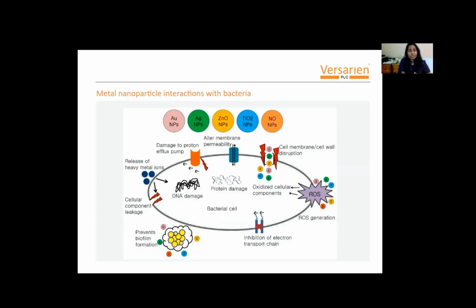Then to talk about the metal nanoparticles, for example in graphene-metal nanoparticle hybrids, the most active ingredient here is the metal species. Release of heavy metal ions can happen into the cell, damaging the DNA and protein. It can also cause damage to the cell wall, and the generation of reactive oxygen species can damage the internal cell structure. So altogether, they break the cell structure and prevent biofilm formation. This is more like a chemical interaction than a physical inhibition of microbial growth.